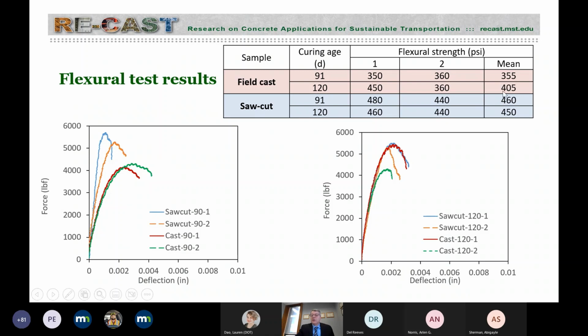We noticed that the flexure strength is lower than what you would expect. When I showed you earlier in the presentation the table, we're talking about 640 up to 900 PSI flexure strengths. And here we have really half of those numbers. But again, the water to cement ratio, and there was only cement used in this case, no fly ash, relatively low cement content, and the water cement ratio was 0.52, which is on the high end.